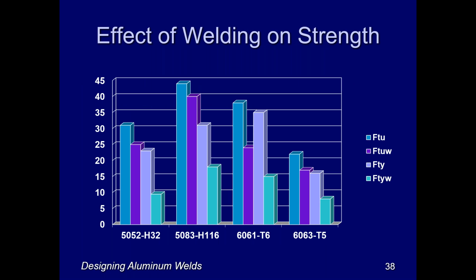Well, so what does that do to the strength of the base metal? Well, I've got 4 examples here. 2 of them are plates, 5052 and 5083, not extrusions. And the other 2 are 6000 series extrudable parts, like 6061 or 6063. And just to give an example here, for 6061, if I have it in the T6 condition before welding, and it's an extrusion with a 38 KSI minimum tensile ultimate, I go and I weld it. Well, I drop the strength down to 24 KSI. So take a big whack. And that reduction in strength is not something that I can overlook. I've got to factor that into the design. And not only that, the yield strength goes down even more. It goes from 35 KSI down to 15 KSI, less than half. And again, that can't be overlooked. It must be accounted for in the design.